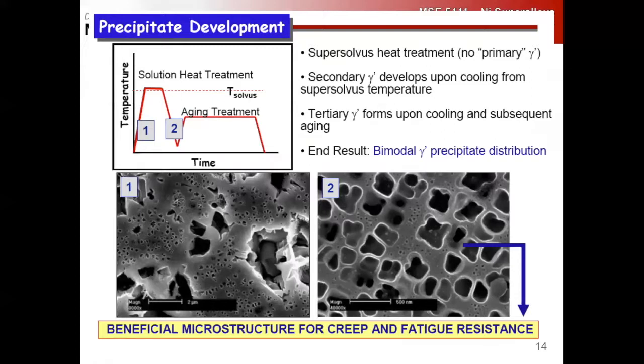So if we look at our typical treatment, here we have sort of as cast, right? We've got these large gamma prime regions, very heterogeneous structure. The typical treatment is to go up, solutionize into the gamma phase, dissolve all the gamma prime, cool down, right? And then have an aging treatment. And if we look at the structure after cooling, here we see our secondary gamma prime particles. Here's our tertiary gamma prime. And this is a disc alloy, which is characterized, disc alloys typically have very high gamma prime volume fractions, right?